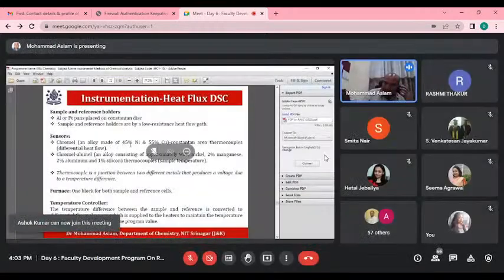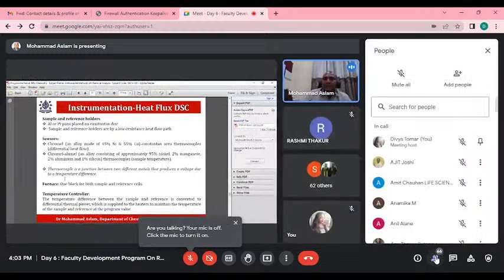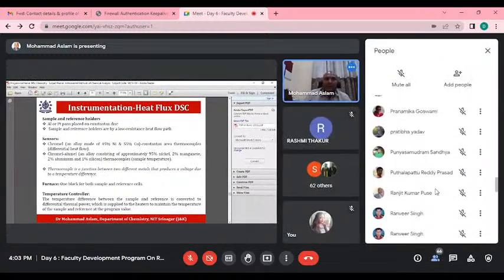So mostly this chromel, that is an alloy of nickel and copper, and Constantan, alumel, a nickel alloy, 95% nickel, 2% manganese, aluminum and silicon. These are thermocouples generally used. Thermocouple basically is a junction between two different metals which produce a voltage due to a temperature difference, that